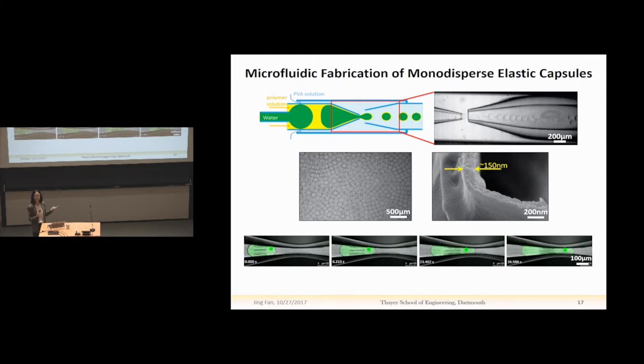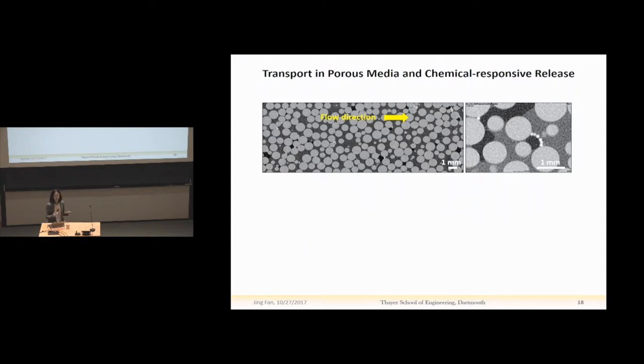Here we use a green fluorescent dye to represent the cargo. And next, we want to characterize their transport in a real porous media instead of just in a single channel. So what we do is construct a model porous media by randomly packing glass beads into a column. And then we first of all saturate this column, this model porous media, with a model oil, which is a mixture of mineral oil and colloid to mimic the crude oil. And then after we saturate it with oil, we inject water.